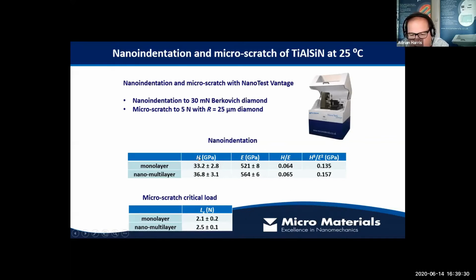So far we've got a nano multi-layer coating which is harder and stiffer than the monolayer counterpart. Critically, putting the absolute values to one side and looking at the ratio of one to the other, there's a suggestion in the indentation response that the multi-layer will be tribologically superior, and there's some suggestion from our scratch testing that that's a reasonable prediction.